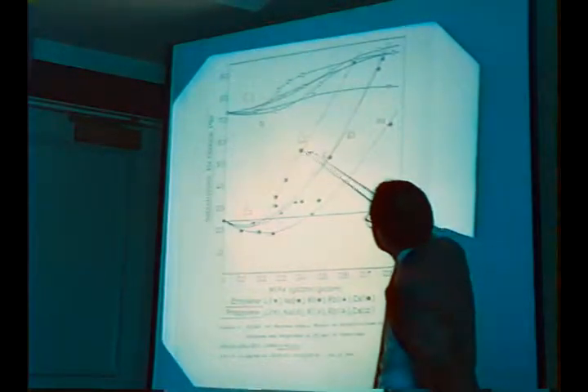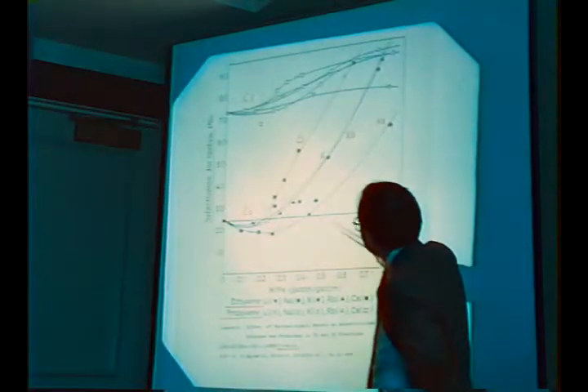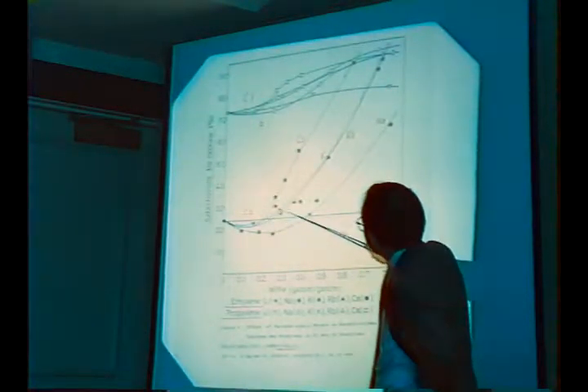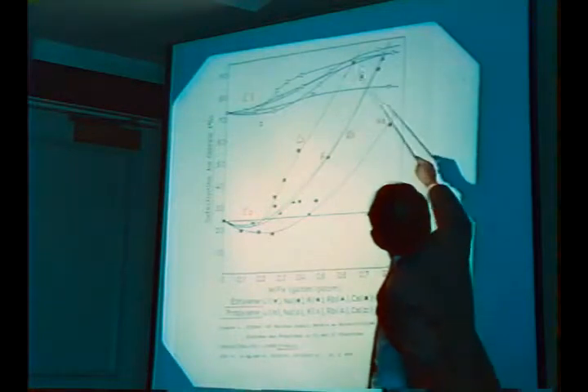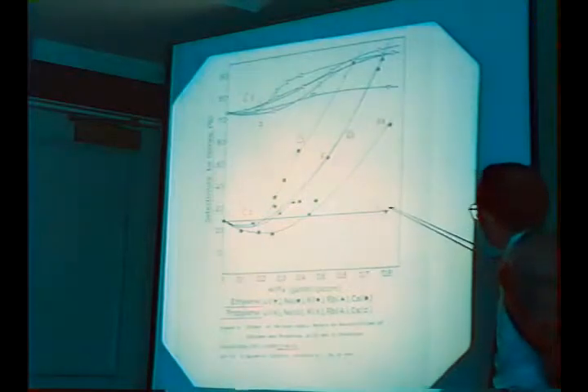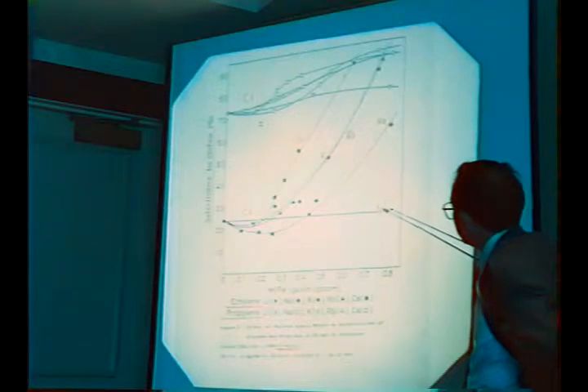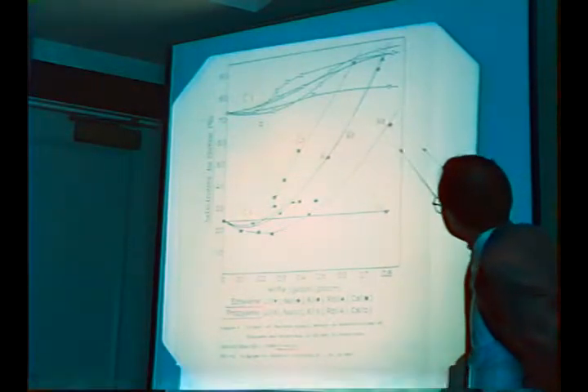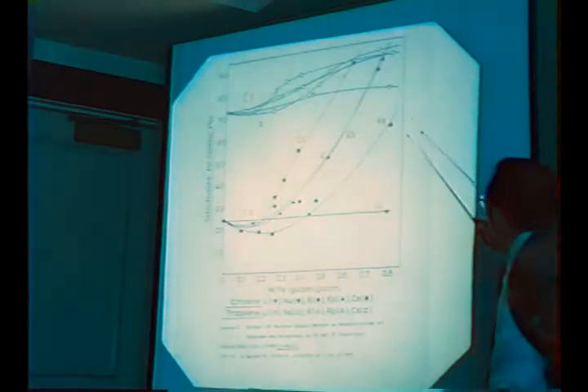And with cesium, potassium, magnesium, in this case, C2 ethylene selectivity is sharply increased to finally 90%. And this lithium hydroxide does not affect the C2 ethylene selectivity. Sodium hydroxide has a weak effect on C2 olefin ethylene selectivity.